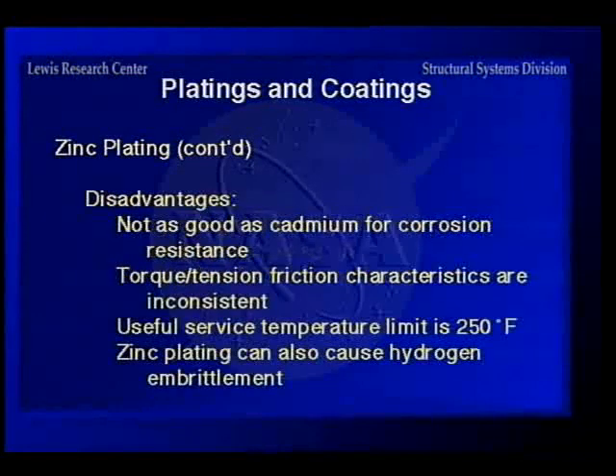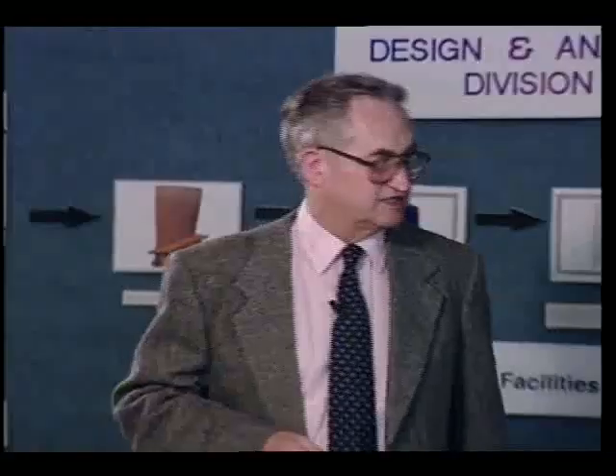And the torque tension friction characteristics, in other words, when you're torquing up a fastener, you can get such a variation in the coefficient of friction that you can get in real trouble on knowing what load you're putting on it. And here's one of the other bad things about it. It has a useful temperature limit of only about 250 degrees, so you can't use it at all where you have elevated temperatures. And it can cause hydrogen embrittlement, although it's not as serious a problem as it is with cadmium.